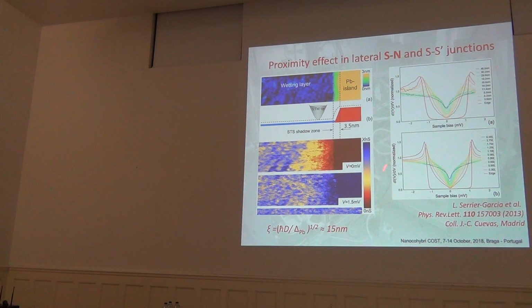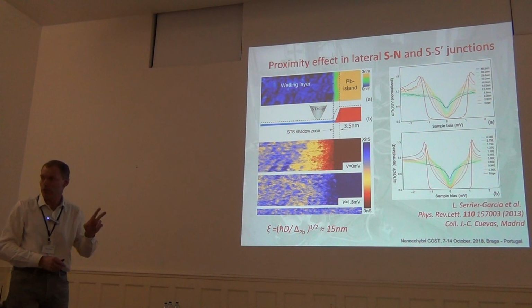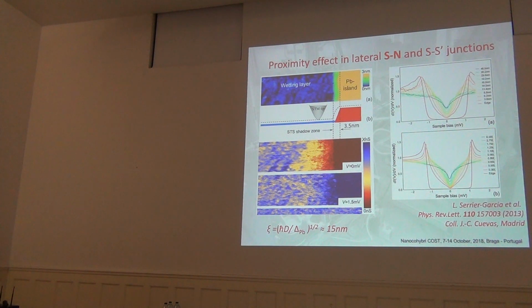And this is a theoretical consideration by Usadel theory. So in a diffusive wetting layer, which is a disordered amorphous layer, we have a so-called dirty limit proximity effect, where we have superconducting correlations, not a superconducting gap. There is no superconducting gap in the proximity effect, there is no superconductivity, there are no Cooper pairs, there are only Andreev quasi-particles, okay? For instance, here you see that immediately you go from here to here, no gap anymore. And theoretically, it's just one point in which you get a zero conductance. You have always excitations outside the superconductor.